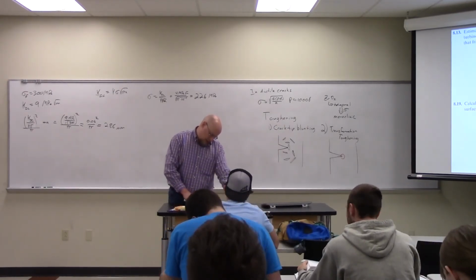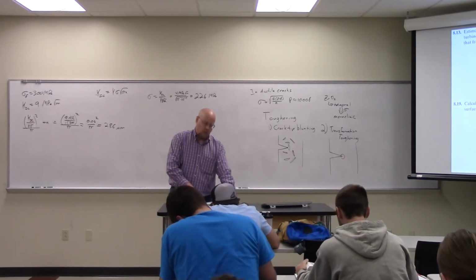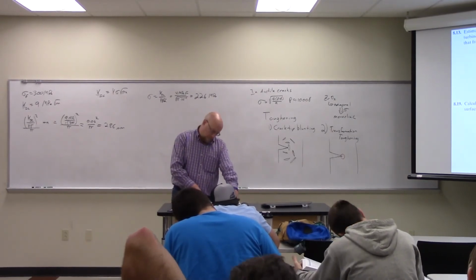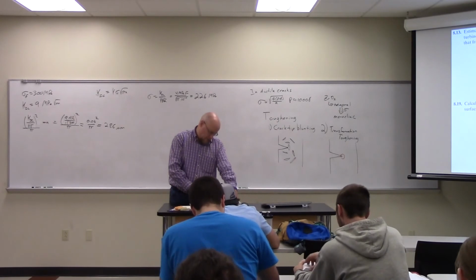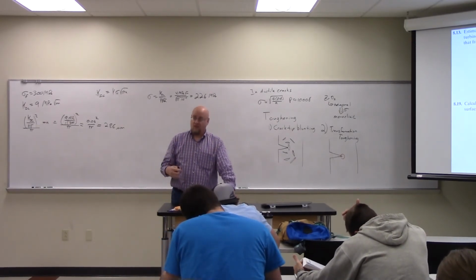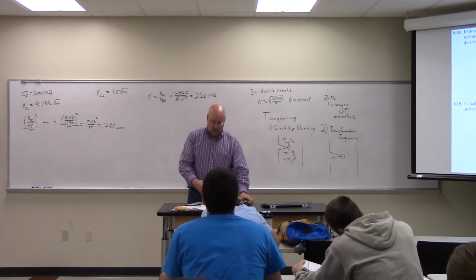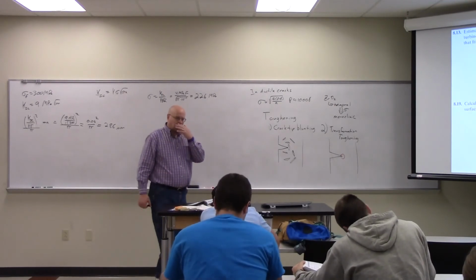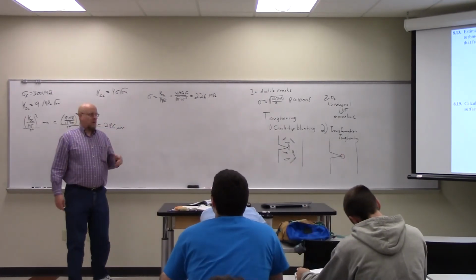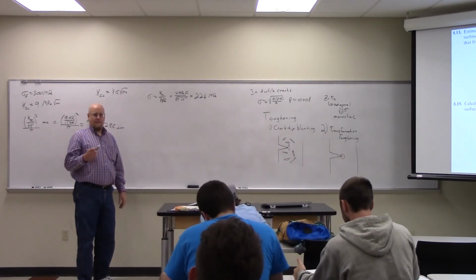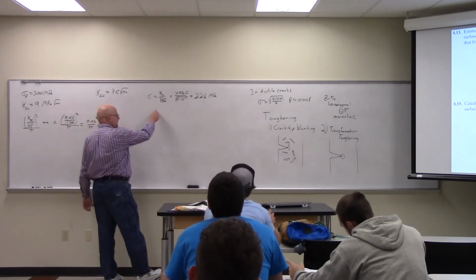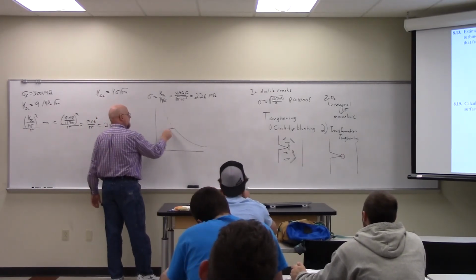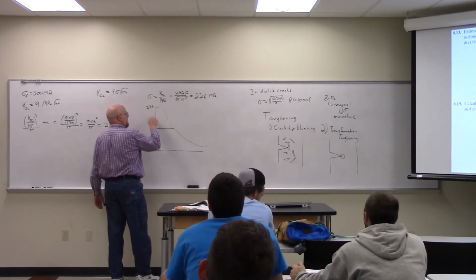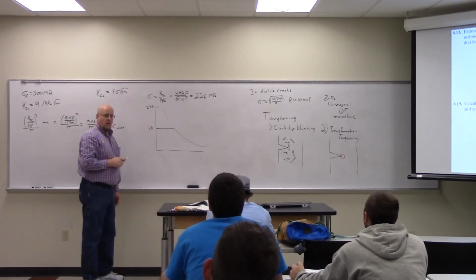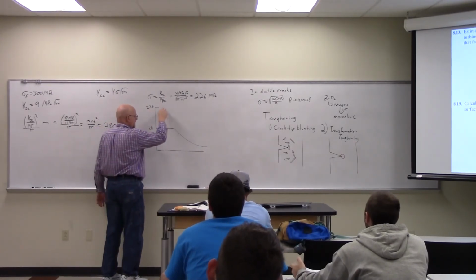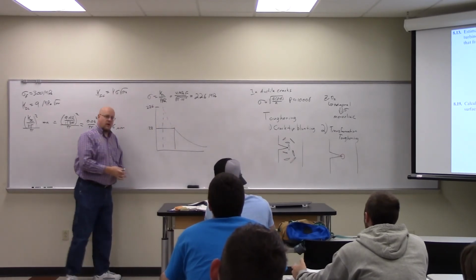The tensile strength of ABS is between 28 and 48 megapascals. So what does this 100 micron defect say? Actually, I'll let you tell me. It multiplies the stress by like 5-ish. It decreases the strength. Never mind, it's a relatively small crack. In my graph, 226 is up here, 28 is down here. Never mind the actual scale, what that says is my crack is subcritical. That 100 micron crack is subcritical.